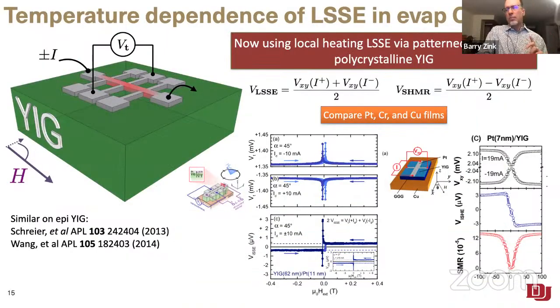Now, we didn't have a ready-made system already running to measure the temperature dependence of the spin-Seebeck effect. Mingfan's setup is a room temperature thing, enormous blocks of copper in a relatively big bulky magnet. I looked at that and thought, well, we've got to shrink this whole thing to fit it into our cryostat so that we can actually measure as a function of temperature. And this is a classic thing where I gave those two grad students I mentioned, Sam Blesser and Matt Natal, a bunch of really bad ideas on how to make that happen.